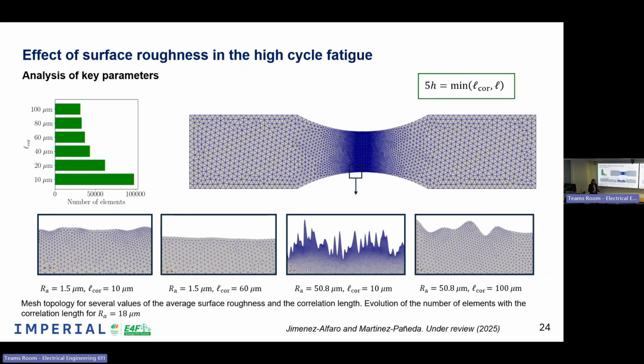However, if we go for extreme values, for example, the average surface roughness with a very low correlation length, then we can see huge peaks, as you can see here. So one of the critical points is how to define the mesh in a way that is accurate. Because if we have those peaks, we need to establish the mesh size around these peaks, no? So we have established a rule, because we have another problem: in the phase field model, we also have a requirement for the mesh size. And we have established a compromise relationship where the mesh size needs 5 elements to define either the correlation length or the phase field length scale, with a minimum of 2. And with this, we ensure that the data is correct.